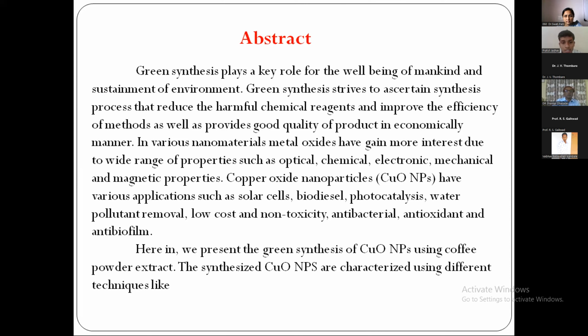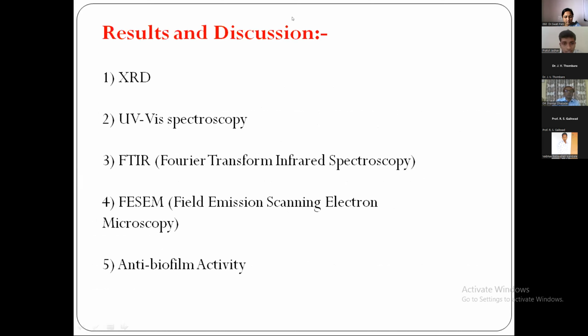Now, in the present study, we present the green synthesis of copper oxide nanoparticles using coffee powder extract. The synthesized copper oxide nanoparticles were characterized using different techniques like XRD, that is X-ray diffraction, then UV visible spectroscopy, then FTIR, that is Fourier transform infrared spectroscopy, FESEM, field emission scanning electron microscopy, and then the copper oxide nanoparticles were further treated for anti-biofilm activity. Here I will discuss one by one.